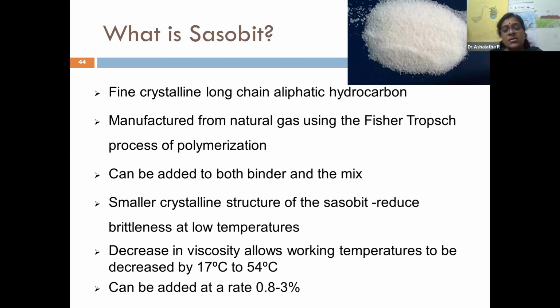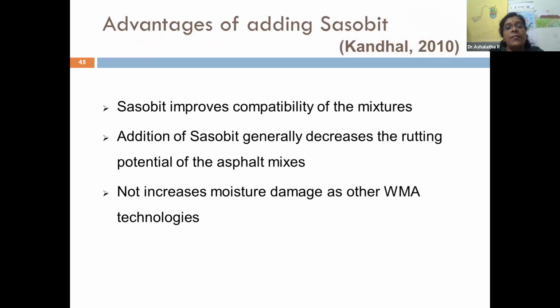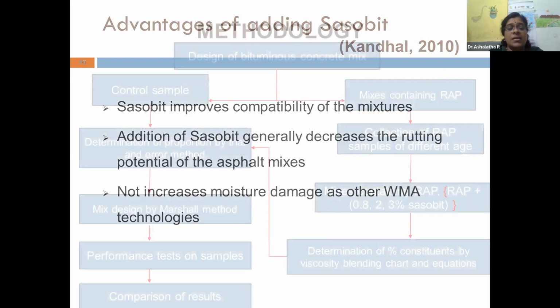It decreases the viscosity and allows the working temperature to be decreased by 17 to 54 degrees centigrade as per literature. It can be added at a rate of 0.8 to 3%. The advantages of using Sasobit are that it improves the compatibility of the mixture and decreases the rutting potential of asphalt mixes, as the literature says. But it does not increase moisture damage as other WMA technologies do.